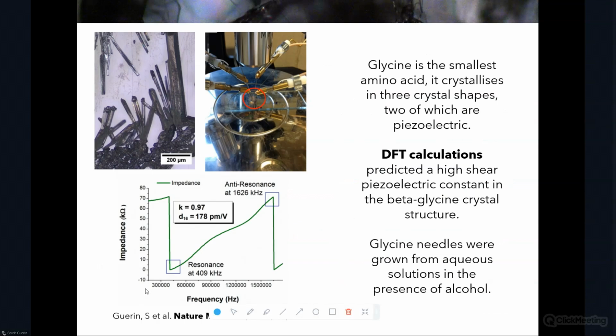So how that led us into this field was when I first developed these models back in 2017, we started to use glycine as a case study. Glycine is polymorphic. One of its polymorphs, alpha-glycine, is centrosymmetric, which makes a nice negative control. Beta-glycine, metastable, is one in which we discovered a very high piezoelectric response, 178 picometers per volt. That was discovered by our models because of the very low shear stiffness in beta-glycine. So in this study, we had to stabilize this metastable polymorph onto a conductive substrate, and then we did our converse piezoelectric testing, where we passed an electric field through our little slice of crystal, caused it to resonate, and then derived the piezoelectric properties from that.